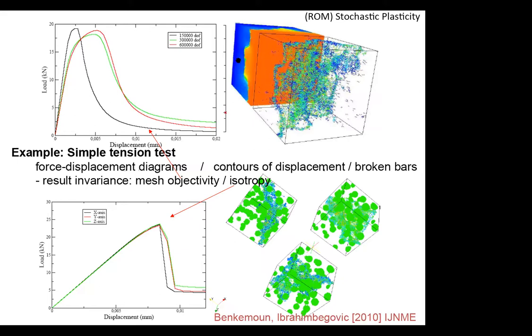So basically, here it's recovered in 2 ways, the fracture, either in terms of these cohesive links which broke. You can see that typically you follow the interface between aggregate and cement because you have a stress concentration at the contact aggregate cement and they are breaking. So the fracture surface is never even. It really follows the whole process of the aggregate. If I pull in X or in Y or in Z direction, I get roughly, it's always one surface which breaks. So I get roughly isotropic behavior. For such a model, it's logical that concrete is an isotropic material.